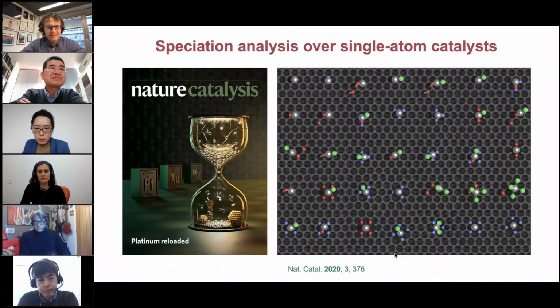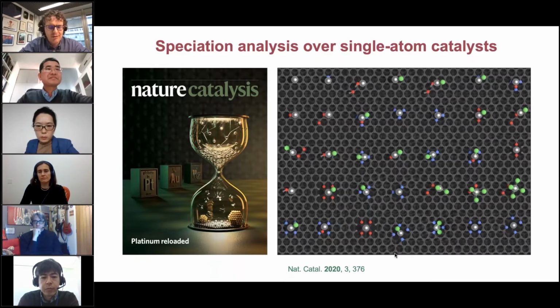I'd like to end with this slide that shows that the versatility and complexity of single-atom heterogeneous catalysts is already pretty astonishing, even if you just have a single atom. That is because the specific location in the solid host, in this case carbon, and the coordination environment determine the electronic properties of the single atom and therefore the reactivity in catalytic applications. The snapshot on the right shows an in-depth speciation analysis of platinum single atoms on activated carbon and nitrogen-doped carbon, conducted to identify the key species that catalyze hydrochlorination of acetylene, which is a key reaction in the manufacture of vinyl chloride.